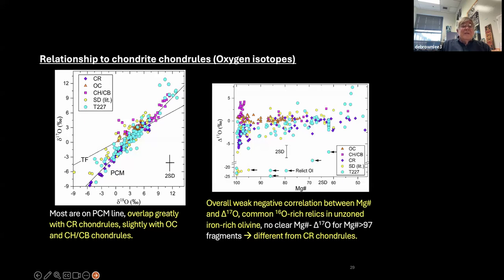So the relations of chondrules to oxygen isotopes. Here's our oxygen isotope data, and there's an overall weak correlation between magnesium number and cap delta O17. There are common O16 rich relics, which are in the lower part of this plot on the right. Going to the plot on the left, the traditional 3 isotope plot, most of the points are on the PCM line and overlap with CR chondrules and slightly overlap with ordinary chondrites and CH and CB chondrules.